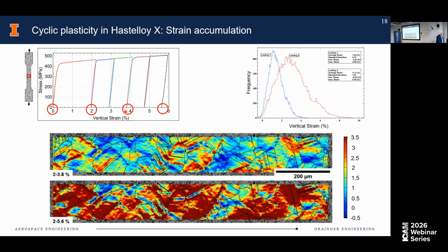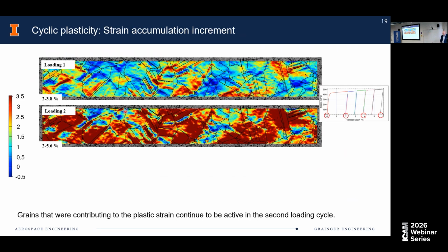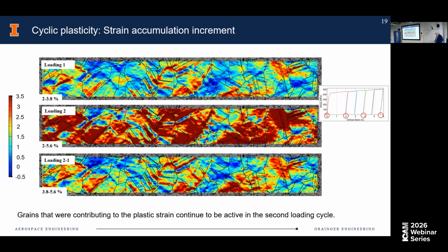What is more interesting is if we look at the difference between them, or the increment between 2 and 4%, and then 2 to 6%, and what happens between 4 and 6%. So essentially the difference between these. What I'm going to show you now is not the difference, but actually the correlation between 4 and 6. So it is an experimental measurement in and of itself. And what you see here is almost identical to the response to the distribution that we obtained in the loading between 2 and 4%.